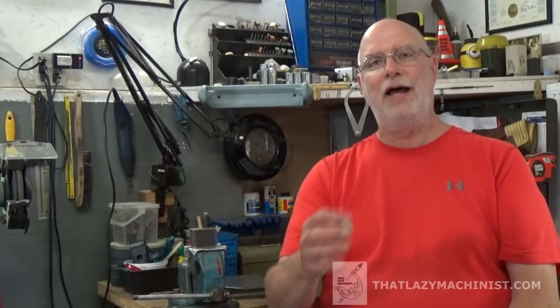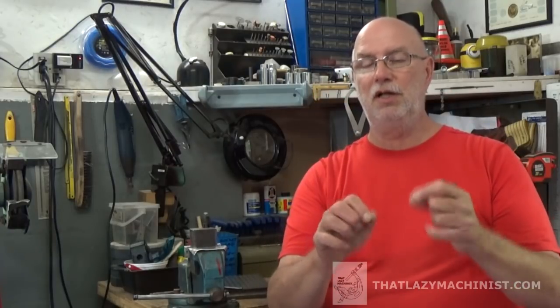Not really. There has to be air in presence for there to be a fire. It's a rapid oxidization, basically. So if I dunk the part in oil and keep it well under the surface of the oil, the part may be very hot, but there is no oxygen in there and we will not get an explosion. Remember, I am using specialized heat treatment oils. Don't do this with any other type of oil. It is very, very dangerous. Okay, that being said, I keep it well under the surface.